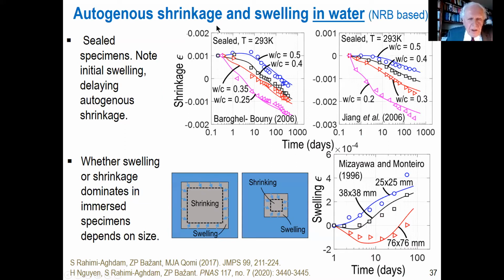Now this gets complicated when you put the specimen in water. If there is water, shrinkage is prevented and swelling prevails. And that's actually where you need the assumption that concrete hydration is always expansive. Otherwise, you could not model swelling.